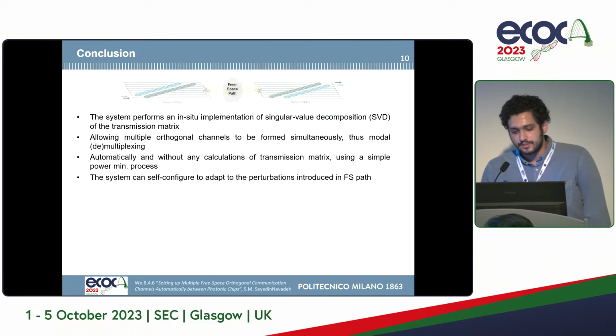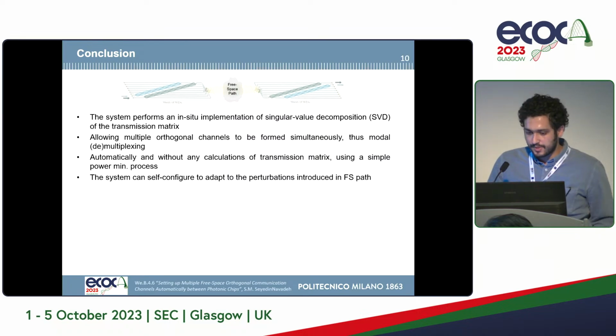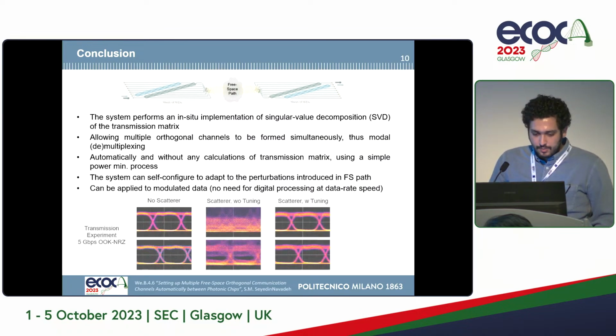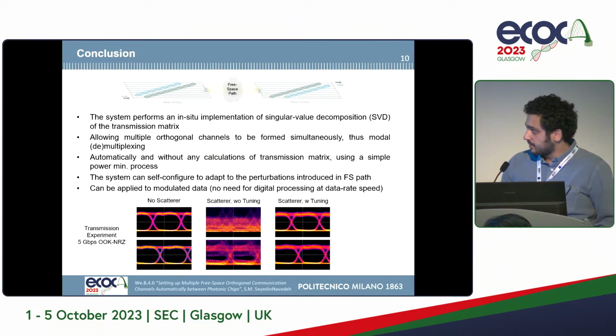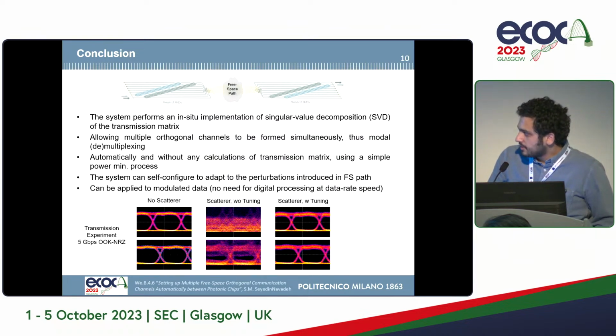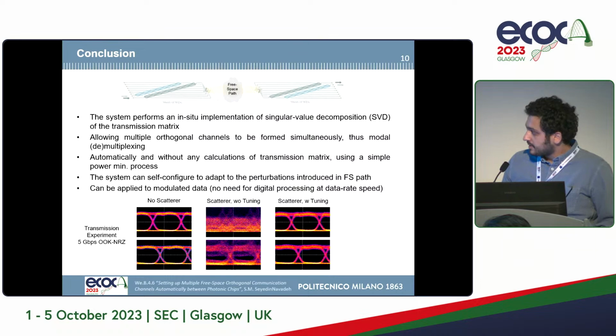This system can self-configure to adapt to the perturbations introduced in the free space path. And this can be applied to the modulated signal, as we are demonstrating here. We use a 5 gigabit per second OOK NRZ signal. So without the scatterer, this is a reference. We put the scatterer without tuning, we get these eye diagrams. Once we tune the system, we get these eyes open again.